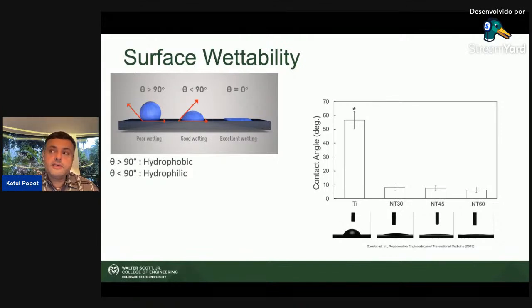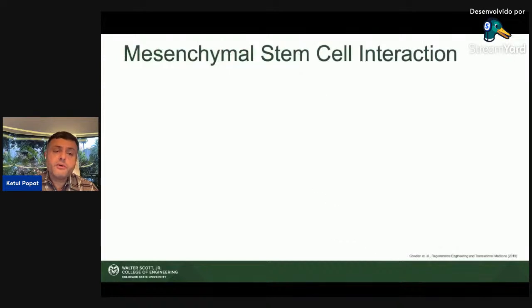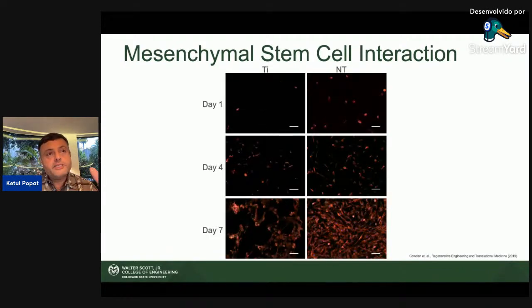The interesting thing about this is that when cells come on the surface, they can spread. When protein comes on the surface, it can spread, and that is really important eventually for the integration of the implant with the tissue. So it's very important to have that. A lot of our work has been looking at how mesenchymal stem cells interact with these surfaces. We take the mesenchymal stem cells either from the bone marrow or from the adipose tissue, the fat tissue. We put the cells on these surfaces, and then we see what happens to the cells. Are the cells able to spread? Are they able to grow? And we consistently find that with nanotubes, we have much better cell growth. This is a fluorescence microscopy image.